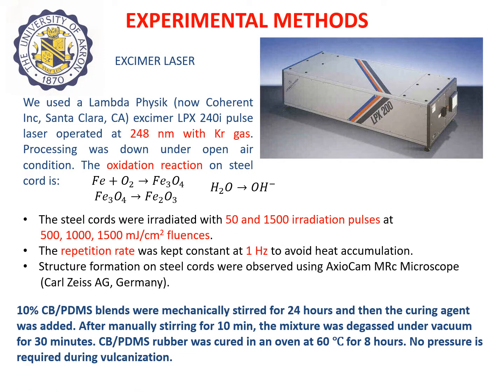The excimer laser we used is a 248 nanometer krypton fluoride gas laser. We applied it in open air, so it does cause oxidation, which is considered by some researchers as an advantageous layer for adhesion. We irradiated the cords using 50 to 1500 pulses, and the fluence was varied between 500 to 1500. The repetition rate was kept constant at 1 Hertz to avoid heat accumulation. And we used an optical microscope to observe the surface features.